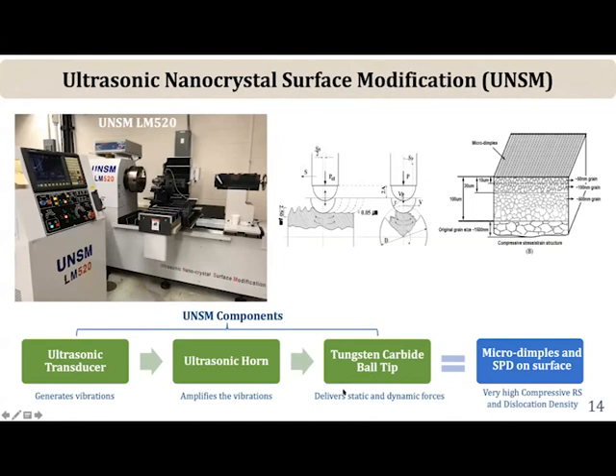The other technique is basically ultrasonic nanocrystal surface modification. So the difference is that this is really a technique for severe plastic deformation of the surface. It uses a tungsten carbide ball, and you impact the surface at very high frequency, on the order of 20,000 to about 40,000 times per second, and the tungsten carbide tool is driven ultrasonically. Basically, it is just like shot peening and even like roller burnishing, I would say. It's really a variation of that technique.